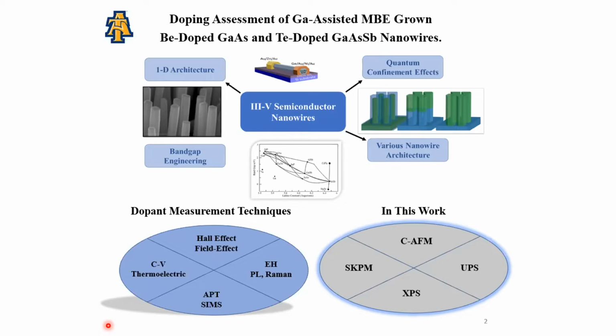Commonly used measurement techniques in thin films for the determination of carrier concentration, namely Hall effect and field effect transistor measurements, require highly sophisticated lithography steps. The uncertainty of the gate capacitance and contact resistance in the case of nanowire FET can further limit the accuracy of carrier mobility and the concentration values. In recent years, several characterization methods have evolved for the assessment of dopants in nanowires. These are secondary ion mass spectrometry, off-axis electron holography, and atom probe tomography, where all these techniques are found to be destructive.